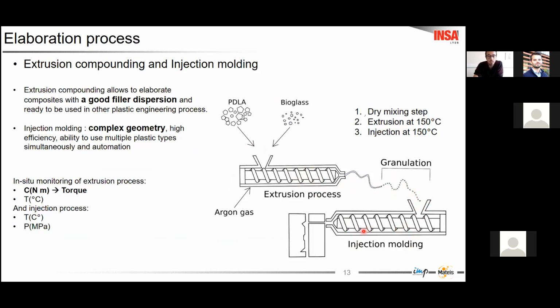The samples were produced by injection molding, and in this process, the elaboration protocol consisted first in drying and mixing the base material. After this, the extrusion process with milling granulation, and finally the injection at low temperature. During this extrusion process, we monitored the torque of the twin screw to follow the evolution of the material at high temperature.